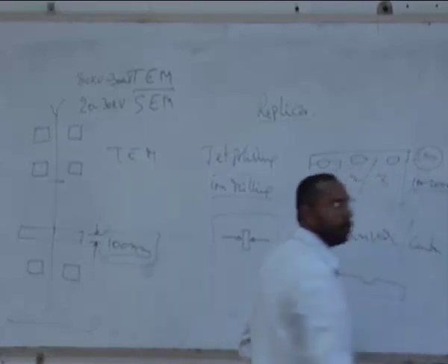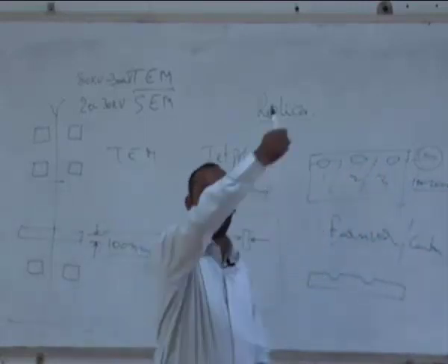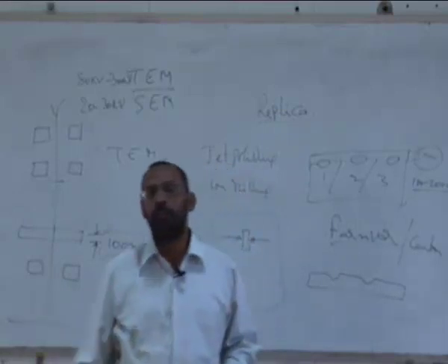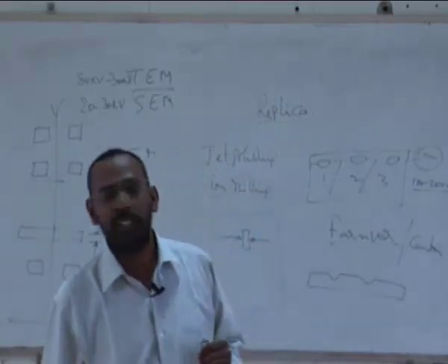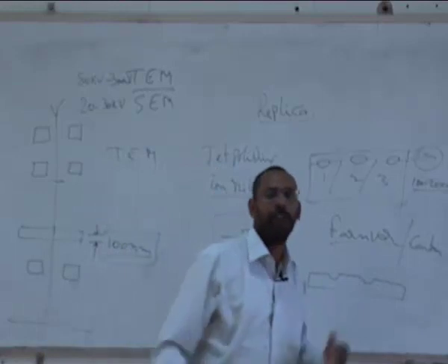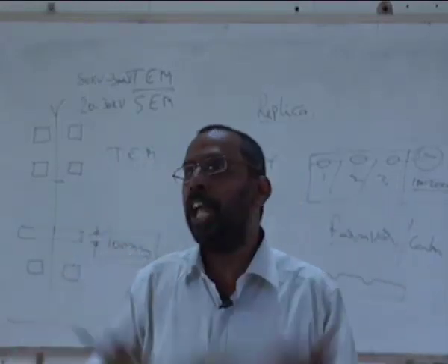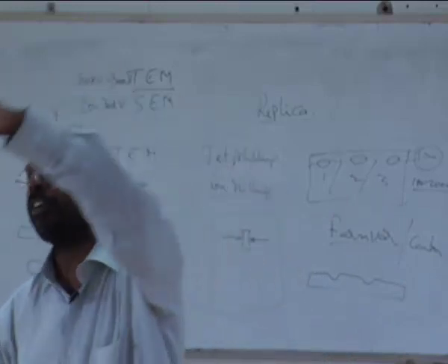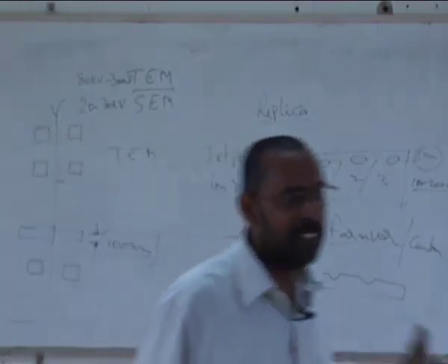If you can produce such a thin film, peel it off, and put it into the microscope, what you actually see is these dimples, and from that you can get an idea of the shape and sizes of those inclusions or precipitates inside your material. You will not be able to know what that particular precipitate is from this technique. You will only know the sizes and shapes and possibly the distribution of those precipitates or inclusions inside your sample.